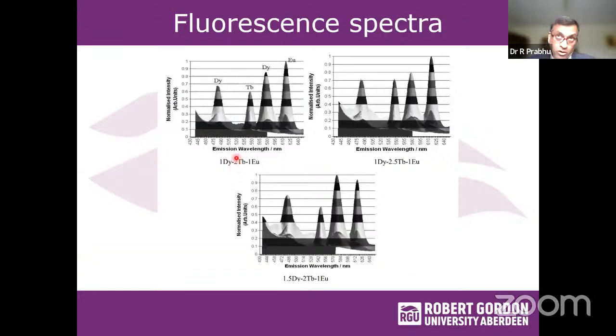Again, we tried to increase the combination, or increase the spectral codes, by changing the concentrations of each of these elements doped in the multi-doped glasses. So in this case, we change dysprosium to 2, then you can see this is the spectral emission associated with Tb. Then we increase Tb from 2 mole percent to 2.5%, and its spectral intensity increased. So by changing the concentration of each of these dopants, you can tailor the spectral intensities of the fluorescent emission. And in this case, this Tb was increased. And if you compare this one with this one, you can see dysprosium emission increases in line with the concentration. So this provides an additional set of spectral codes by varying concentrations of doped elements.